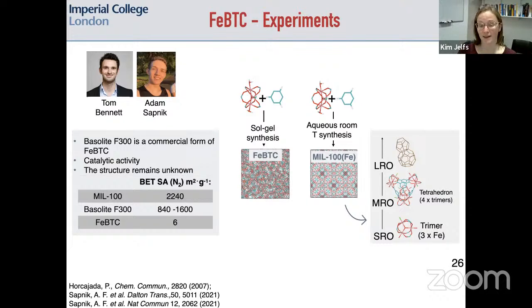So it's this iron FeBTC system, which contains the same building blocks as MIL-100 and also Basolite F300, which is used commercially as a catalyst. The structure of MIL-100 is known, it's crystalline, but for the other systems, this was much less known, and they all have different surface areas and porosity. And so they're made via different synthetic routes. But as I say, they have the same underlying building units.